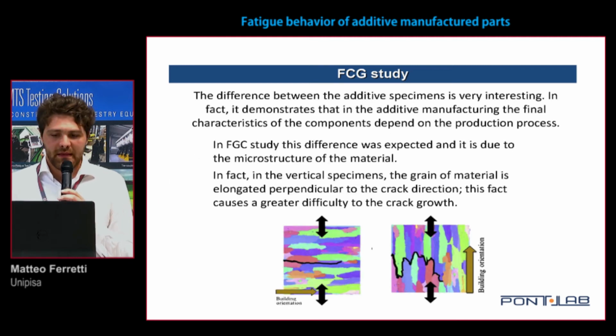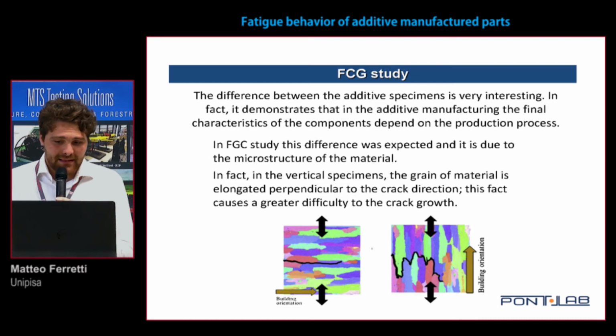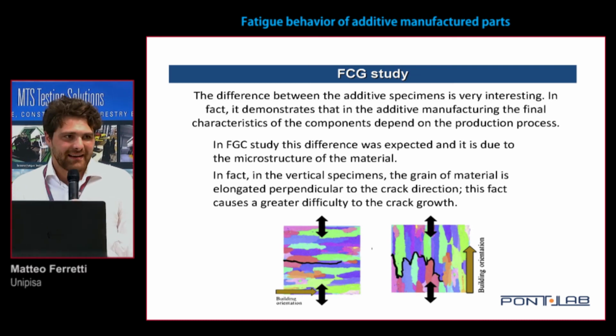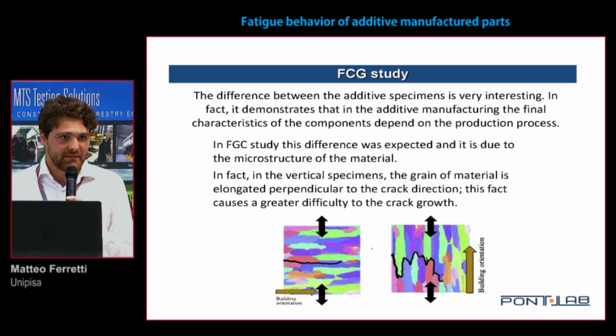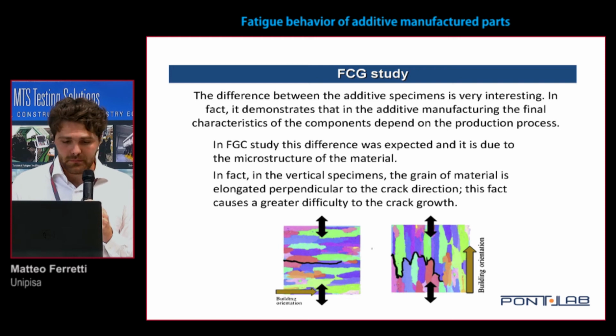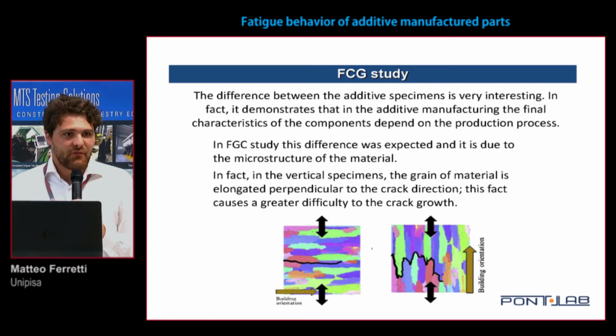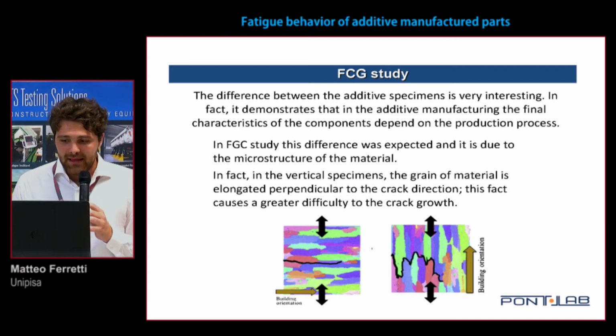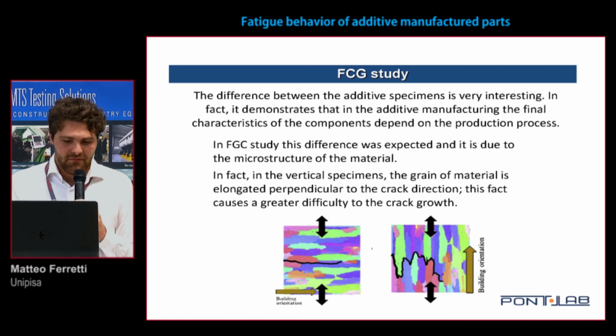The difference between the additive specimens is very interesting, and it demonstrates that in additive manufacturing, the final characteristics of the components depend on the production process, in particular on the building orientation. This difference was expected and is due to the microstructure of the material. In fact, the vertical specimens have the grain elongated perpendicular to the crack direction. The grain is a sort of barrier for the crack, and in fact, the crack growth rate is lower.